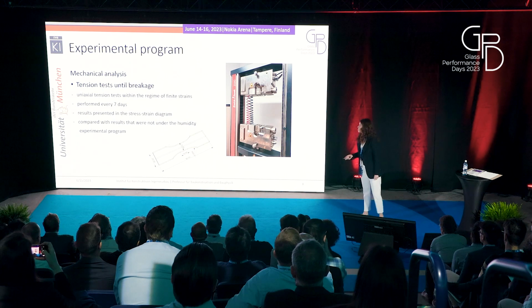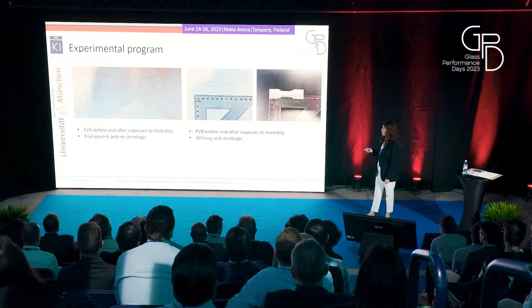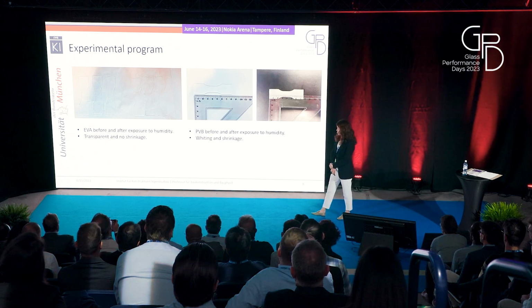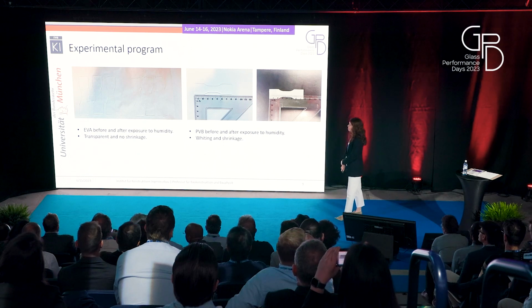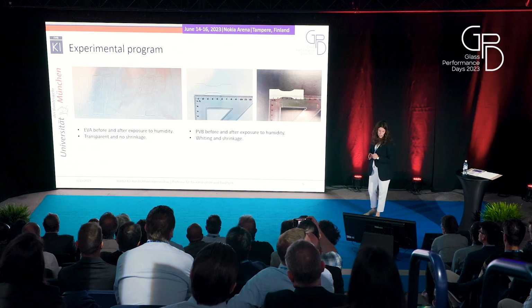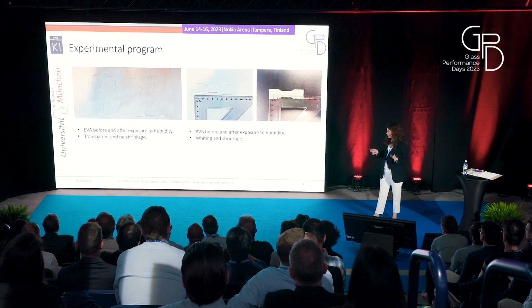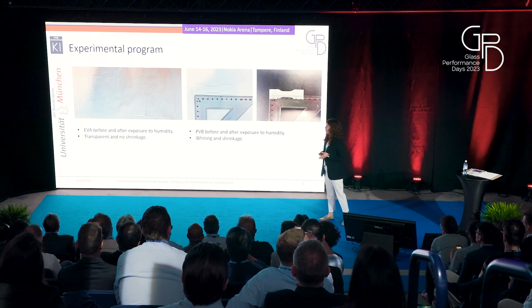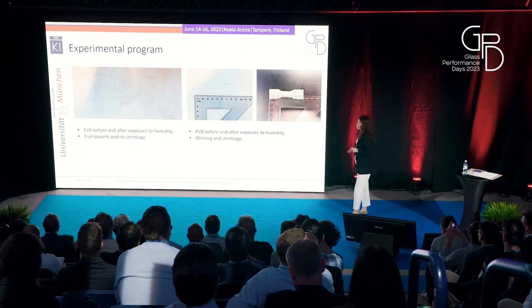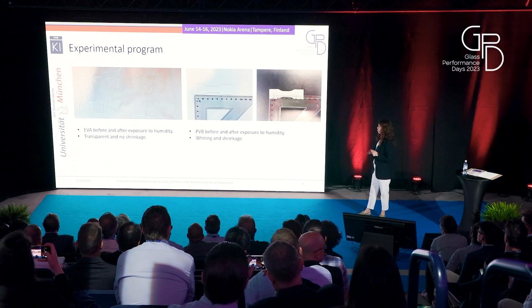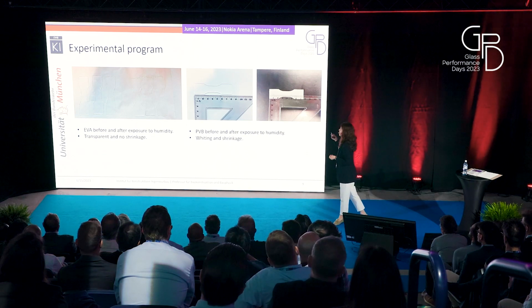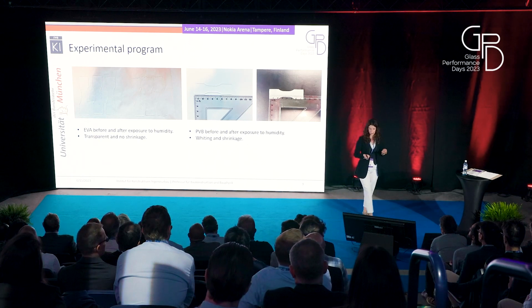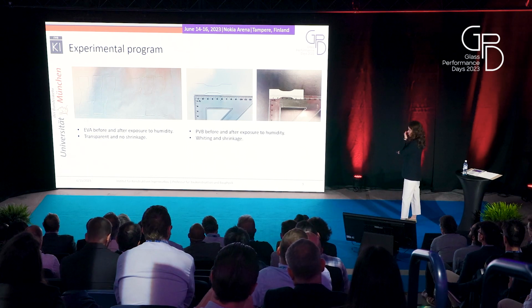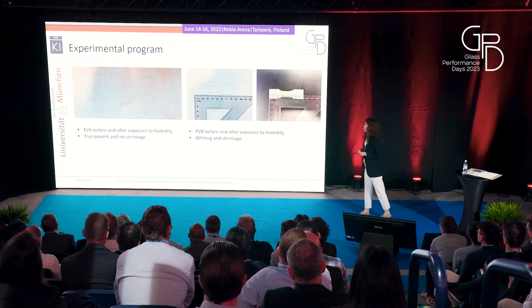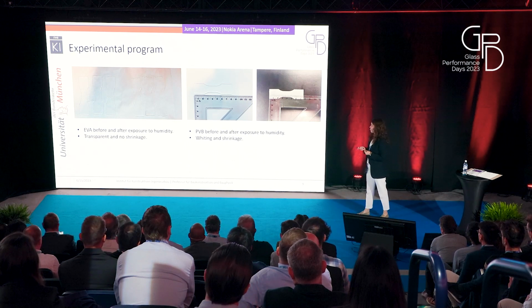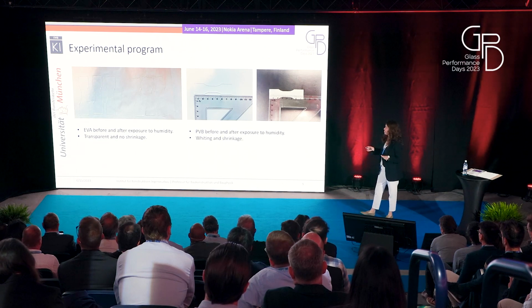So this is our test machine and the geometry of the specimens that we used. I'm sorry, maybe the pictures are not good enough, but I hope you will see what is important to notice here. On the left are the EVA samples before and after exposure to humidity. It's important to notice that they remain transparent. There's no shrinkage. Then on the right side are the photos of the PVB. This is something we expected, but nevertheless, just as a comparison, this is how PVB looks before and after exposure to humidity, and you can see the whitening and also the shrinkage just by being exposed to the humidity program.